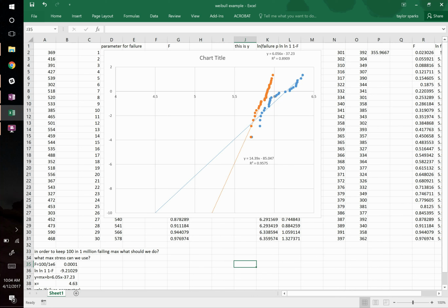This one can actually withstand 5.27, which is how many megapascals, we take e to that. Take e to 5.27. That's 194. So this thing is twice as good basically, right? It's super counterintuitive, right? At first blush, you're like, hey, this thing's got average strength of 450 versus 350. This is a way better material, but because the distribution is broad in this material, it's actually undesirable to use for this scenario.